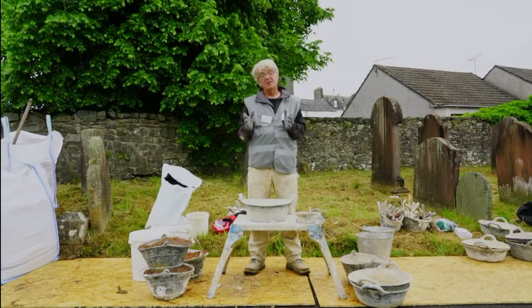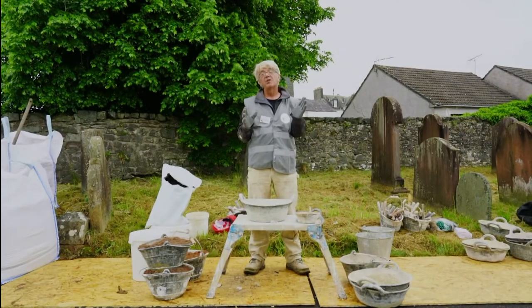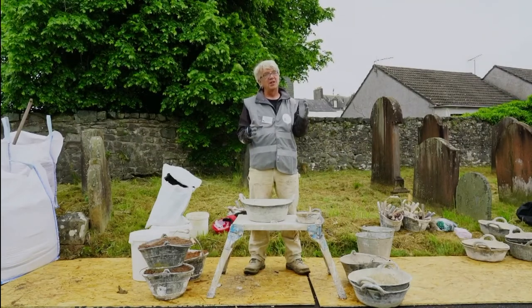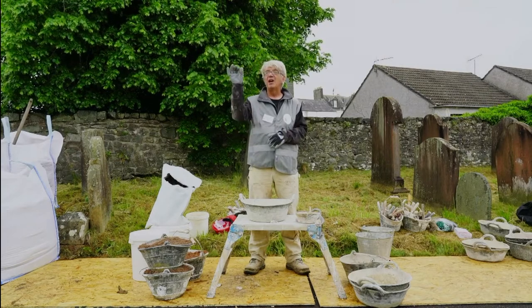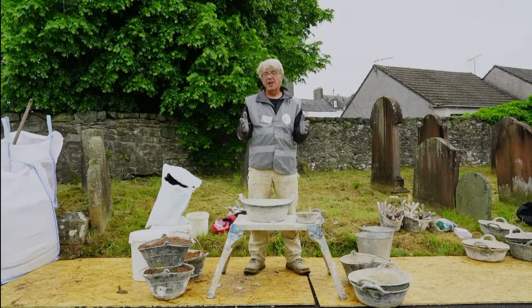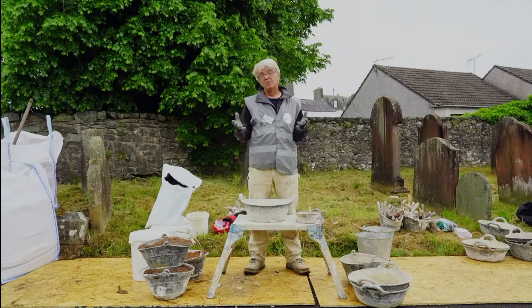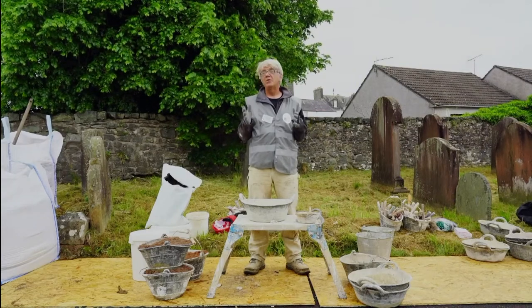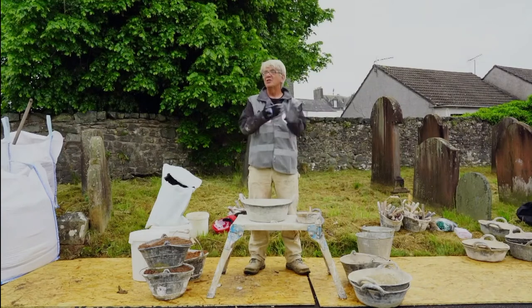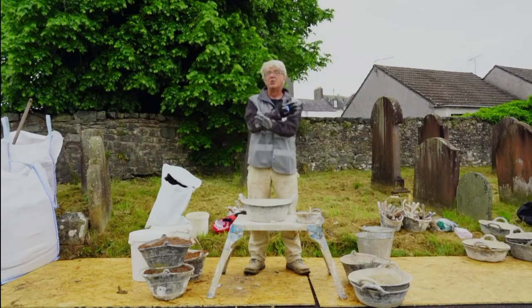The other function that we need mortars to perform is that when they receive water, which, in a capillary active material like we're talking about, won't go very far in from the outside when it's hit by rain, maybe that far, generally speaking, even in intense heavy rain, we need that water to come out as soon as it's dry. Robin Pender at Historic England even argues that even when it's raining, if you've got the right mortar there that is capillary active, the building will be drying as it's wetting. It's not just waiting till it stops raining. Wherever there isn't rain hitting the mortar, water is coming out of that mortar.